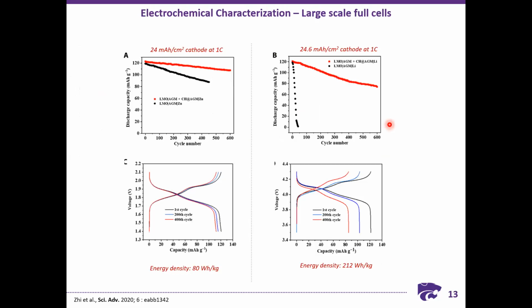So interestingly, they moved ahead to form large scale full cells with a very high loading, because in lab scale level, the electrolyte amount that is being used is quite high, which decreases the energy density of the battery. And also in commercialized batteries, when they move ahead to make commercialized batteries with a very low electrolyte amount to improve the energy density, the performance which is being shown in the half cells or the lab scale level cells may not be reproduced, since the conditions are quite harsh and the batteries won't perform well enough. So they went ahead to make a 24 milliampere per centimeter square cathode, the very high capacity, and they have used a constrained electrolyte amount of around 10 grams per Ah of capacity.